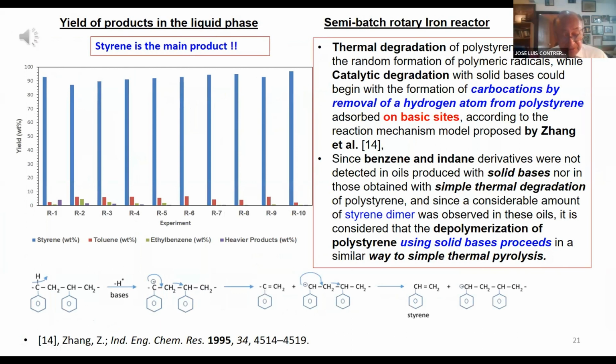Catalytic degradation with solid bases could begin with the formation of carbocations by removal of hydrogen atoms from polystyrene adsorbed on basic sites, according to the reaction mechanism model proposed by Zhang. Thermal pyrolysis without a catalyst could originate with a random formation of polymeric radicals.